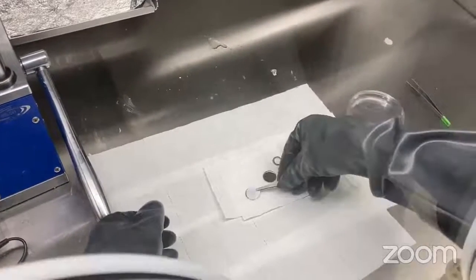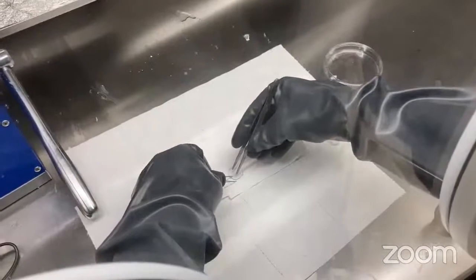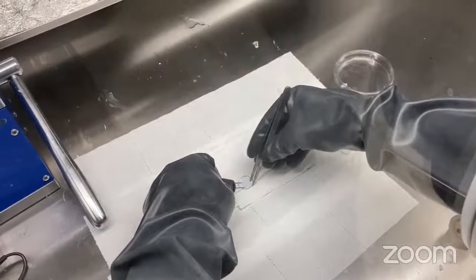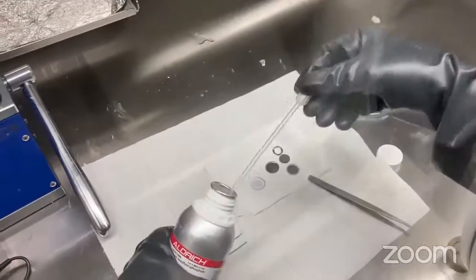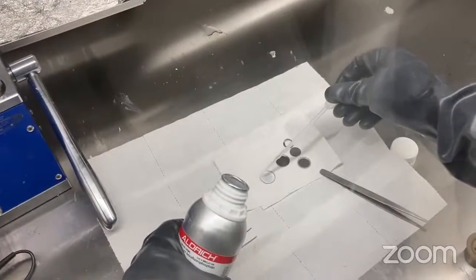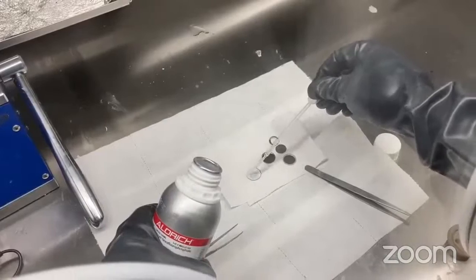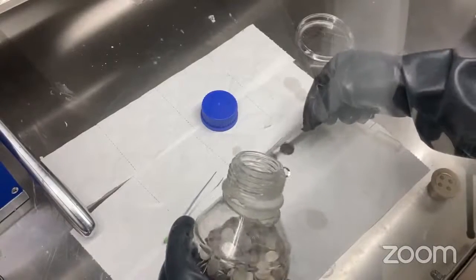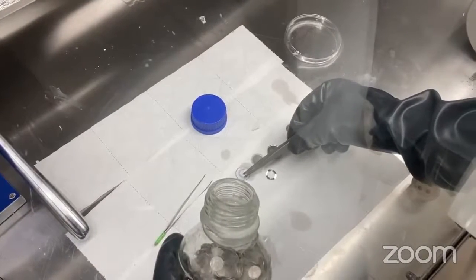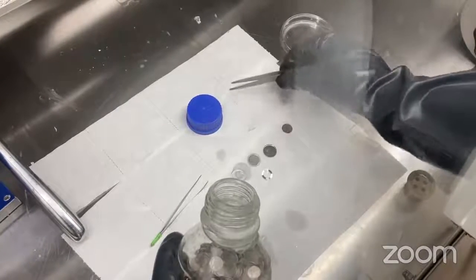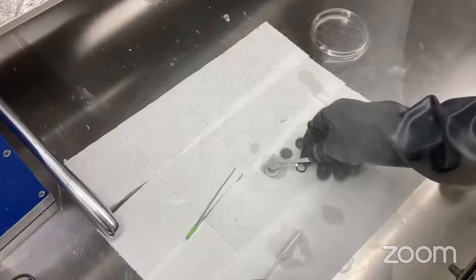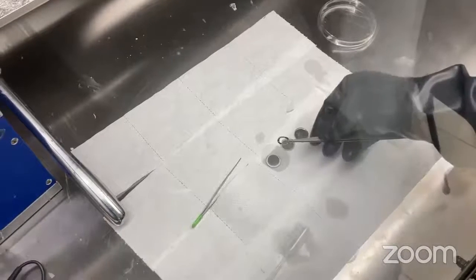Let's start the assembly. Here we are keeping the graphite electrode on the positive case first. Then we put the separator to avoid contact between the two electrodes. Then we are putting lithium-rich electrolyte. After that we are putting lithium metal, then a spacer and spring to make better contact between the two cases.